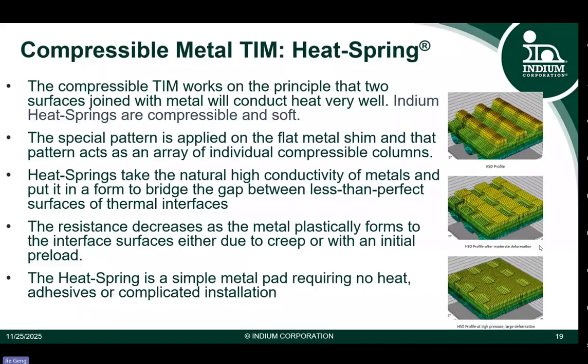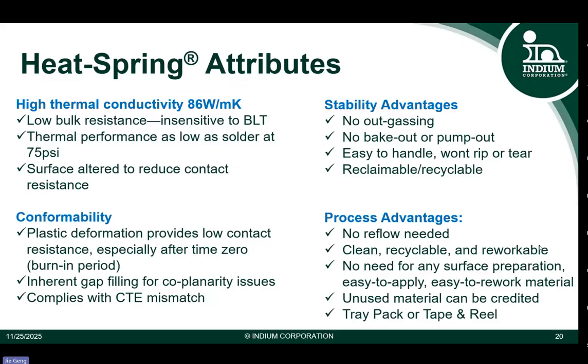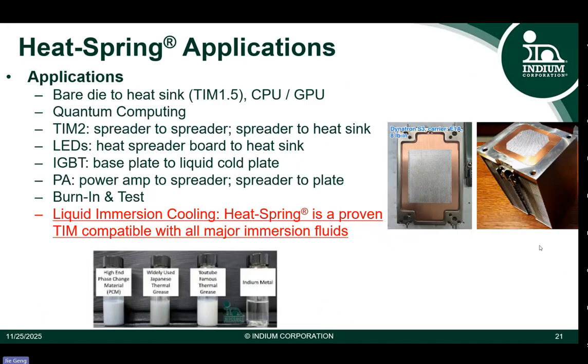Now here I list the attributes for the heat springs. So it's made from indium, so has very high thermal conductivity. And there's no pump out issues and it's easy to handle. And we can provide different thicknesses, so the conformability is pretty good. And you don't need to reflow, so the process is easy to handle. So the major application for the heat spring is TIM 1.5, the bare die to heatsink.